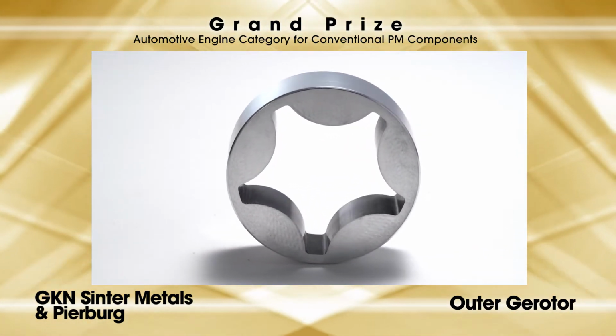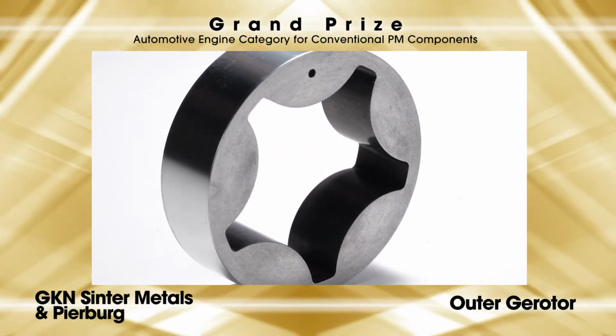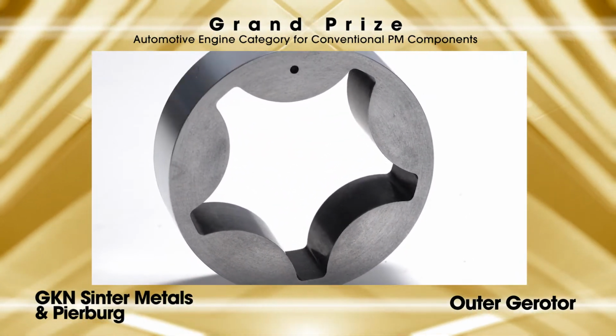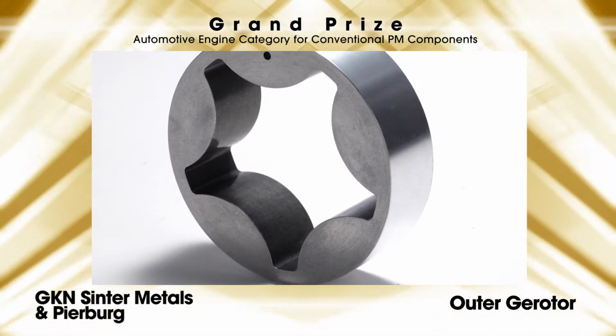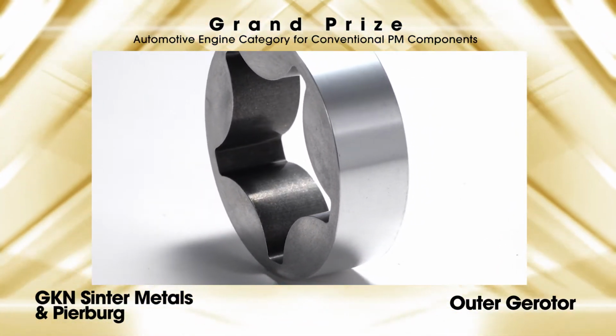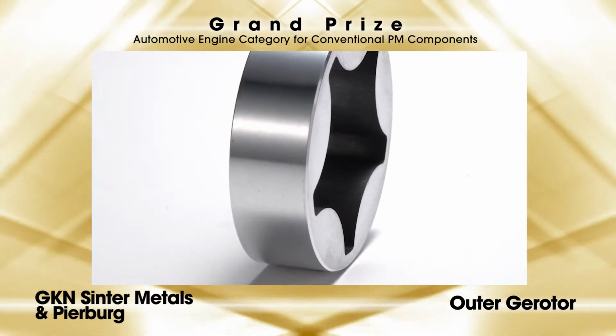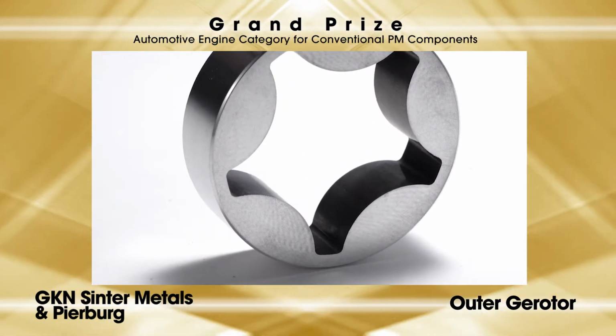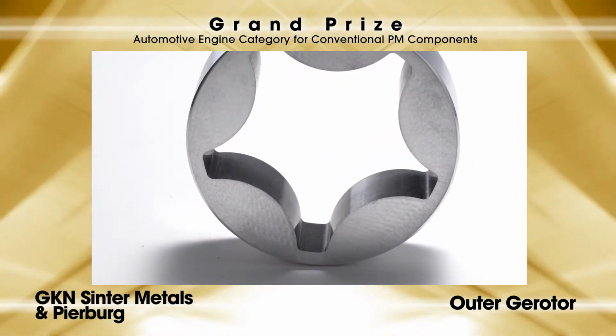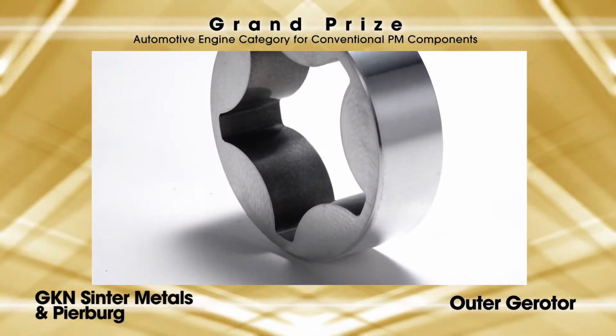It is the first PM aluminum outer gear rotor using dual material aluminum steel pump gears for a production vehicle application. The gear rotor is solution heat treated and artificially aged for optimum mechanical properties. The unique material system retains high strength at the 150 degrees Celsius operating temperature. The inner profile of the gear rotor for this high performance application was critical for it to function in conjunction with the steel inner rotor with a different thermal expansion coefficient.